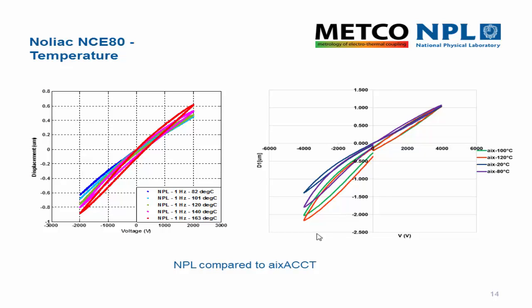Here are some of the measurements. Again, we've seen these results earlier, but I just wanted to show them side by side. On the left we have the NPL interferometer measurements and the aixACCT measurements on the right. These are not directly comparable because we have a difference in the voltage applied. These are 2000 volts, or 1 kV per millimeter, and the aixACCT ones are done at 4000 volts. But if you look at the sizes of the displacement, they are about proportional to the voltage applied, and we see a larger hysteresis in the higher electric field measurements, which is what we would expect. So those two sets of measurements look comparable.